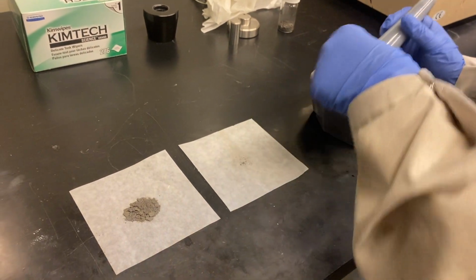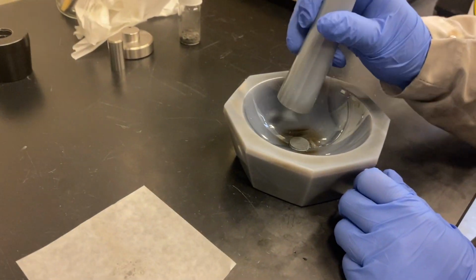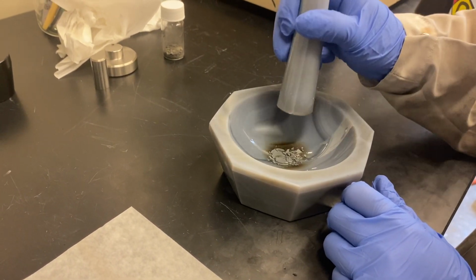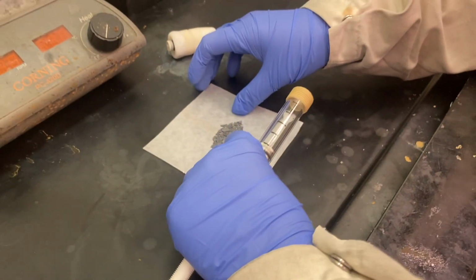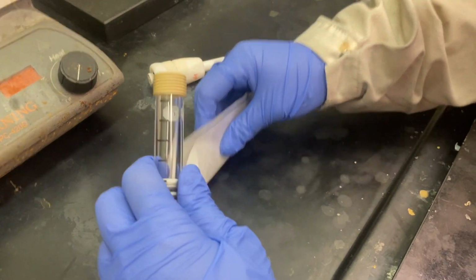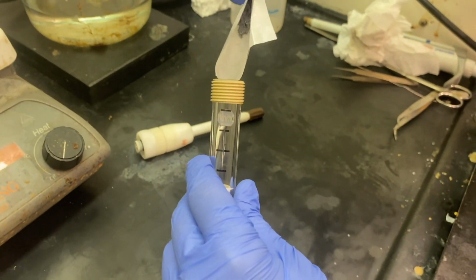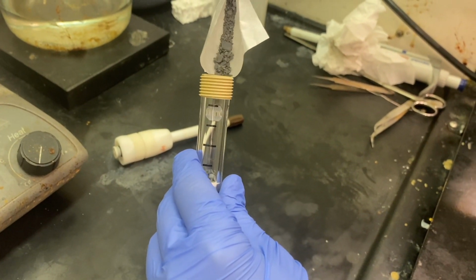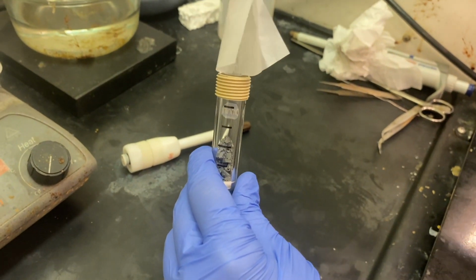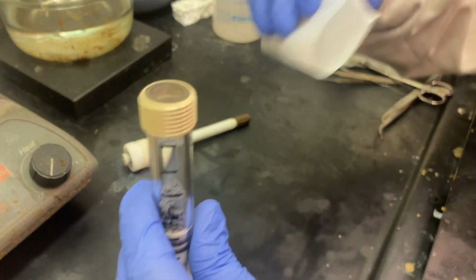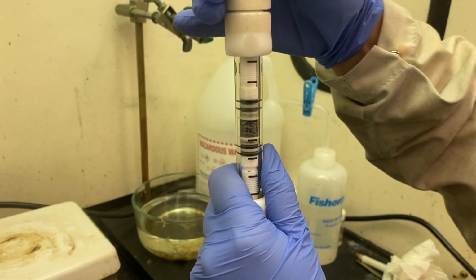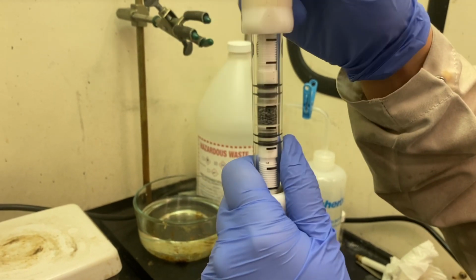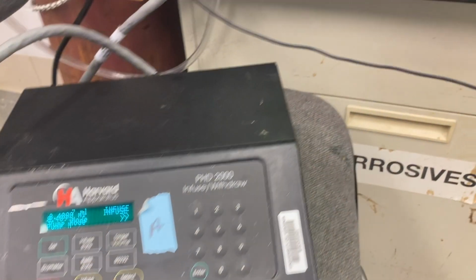Preparation of the intercalation particle packed bed begins by crushing iron phosphate particles. Less than half a gram of this highly selective material is needed per liter of geothermal brine. The particles are loaded into a column, which facilitates contact between the brine and the packed bed particles and affords control over pressure drop. The packed bed is prepared at a consistent bed height to promote reproducibility between experiments.